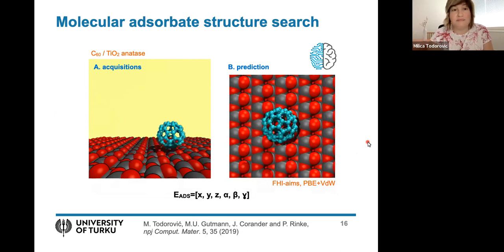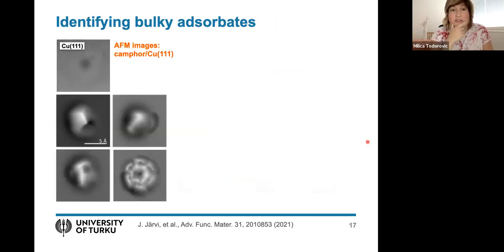So that's how it works. After this, we wanted to do this in a more practical way. And as Michael said, we work a lot with our AFM colleagues, and they were looking to image camphor on copper 111. They deliberately prepared their sample to see camphor in different configurations of adsorption. But when they imaged them, they found they couldn't quite determine what the configurations were. The images were very blurry, and they couldn't identify the atomistic structure underneath.